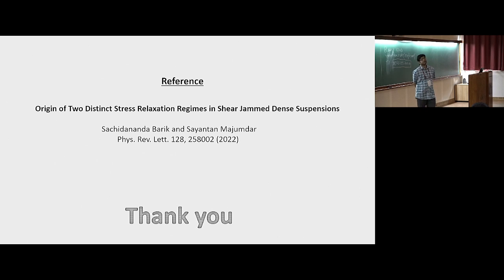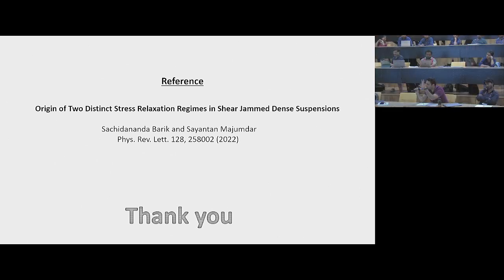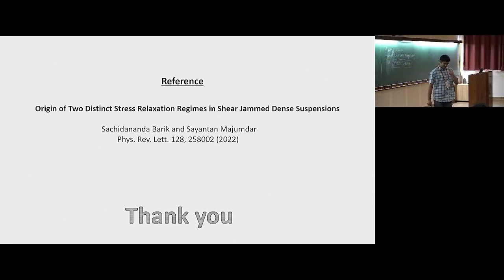And do they also occupy spaces at some defects, albeit in the 2D image that you see? Are they more localized close to defects or something? No, actually, although the particles are fairly monodisperse, it's a disordered packing. After you create those plastic centers, or after they relax, we plotted the g(r). The g(r) doesn't have any signature, and if you look at the local structure, you couldn't find any correlation till now because it's a disordered packing everywhere. So identifying defects is difficult.